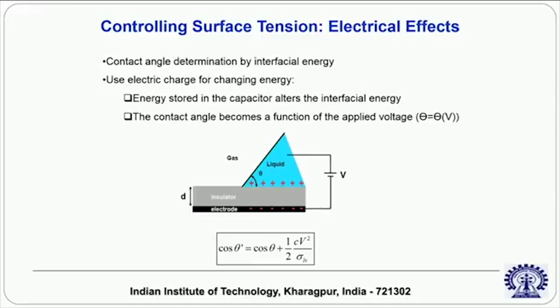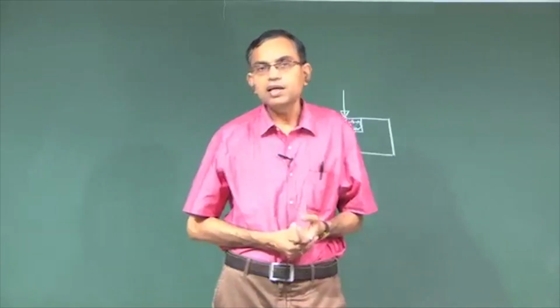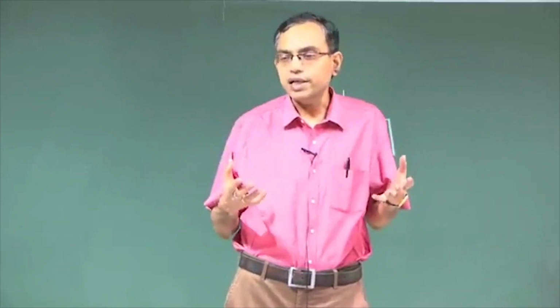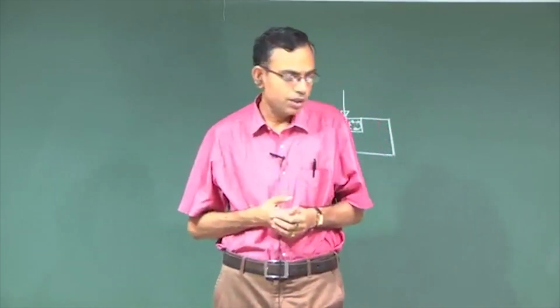The formula says, if we look into it again, the new cos theta is a function of the old cos theta plus a parameter which is proportional to the square of the voltage. So, whatever may be the sign of the voltage, V square is always positive. So, if V square is positive, you will have cos theta prime always greater than cos theta, because capacitance, sigma LV, all those are also positive. That means theta prime is less than theta. So, it is always electrowetting, no matter whether you apply positive bias, negative bias or whatever, it cannot be an increase in contact angle because of the electric field, it is only a decrease in contact angle because of the electric field.